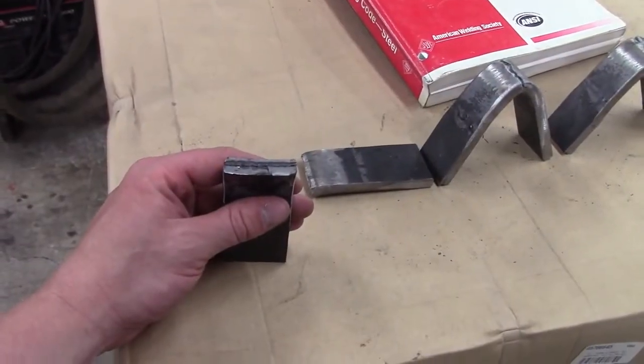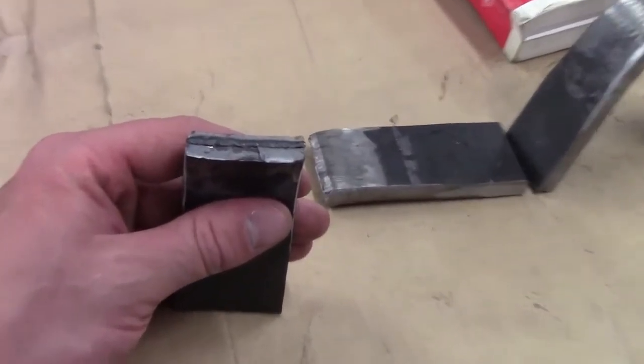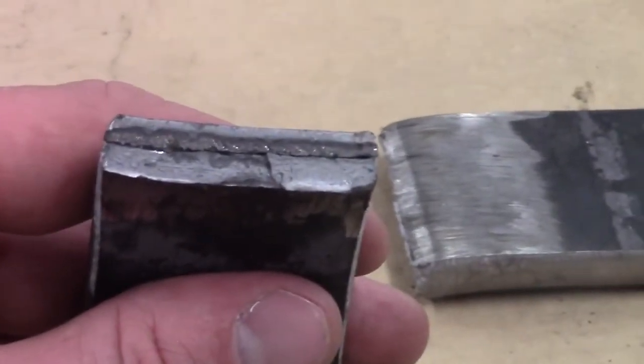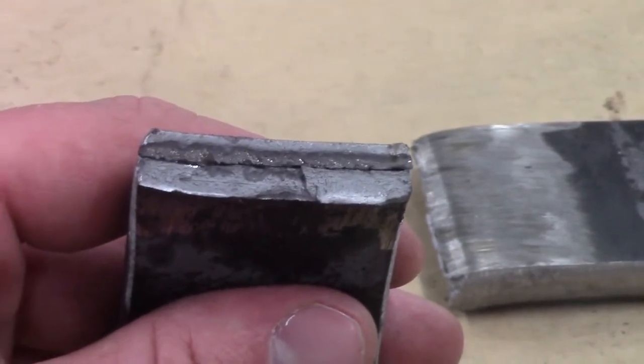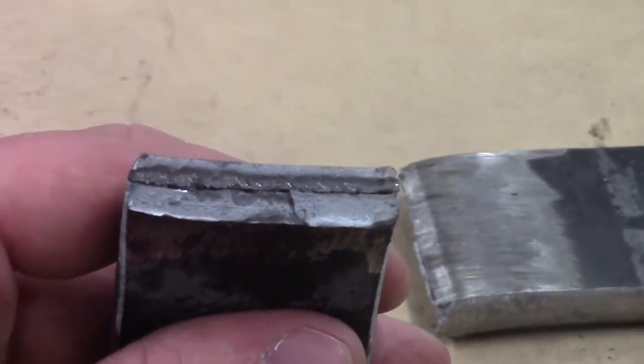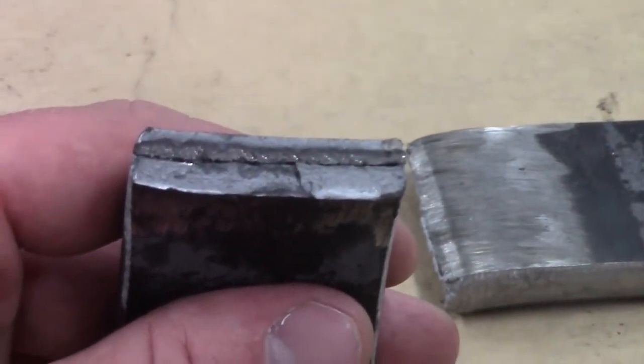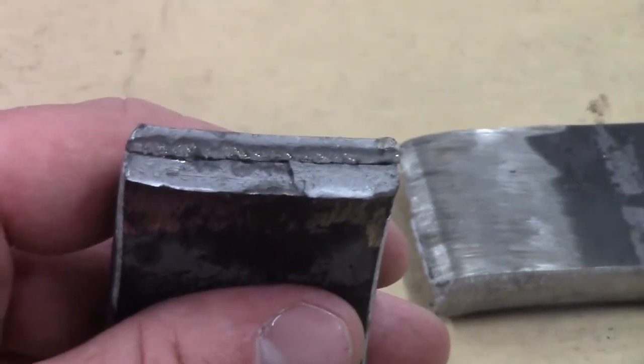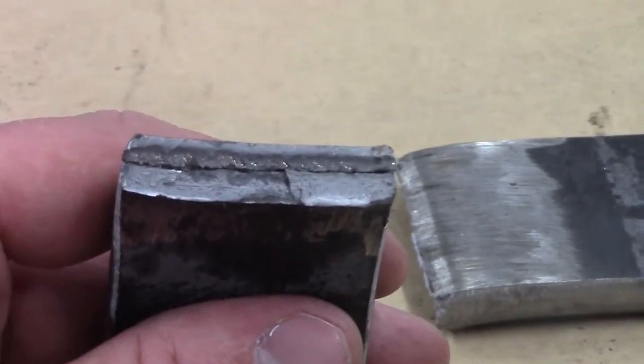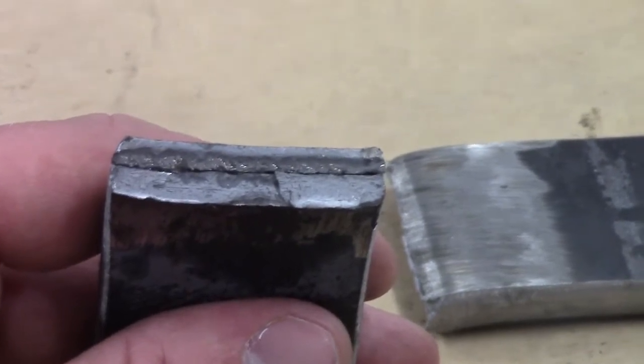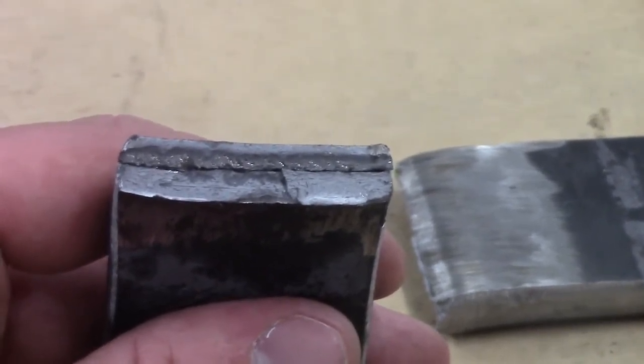Okay, here's the broken piece. We're going to get right in there. See that parting line right there? There was absolutely no fusion there. So basically what you had going on was a great looking weld that didn't fuse all the way through. So you had a line of lack of fusion in the middle of the weld. That's why you do these.